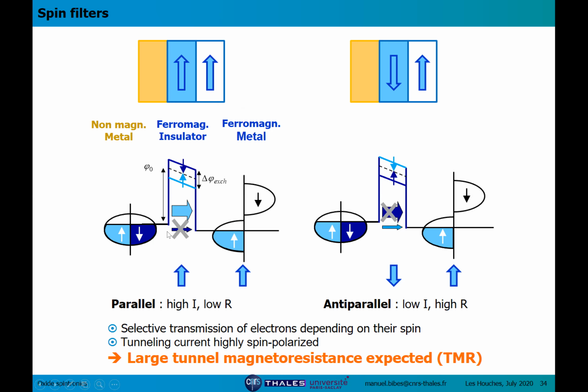Okay, so you filter out electrons according to the spins due to the presence of two barrier heights depending on the spin in the ferromagnetic insulator barrier, and this is why these devices are called spin filters. So if the barrier is sufficiently thick, this filtering effect will be extremely efficient. And at the output of the barrier, you can well achieve almost fully spin polarized current, while you started with a non-polarized current with this non-magnetic metal as your electrode. So you expect to have large TMR.